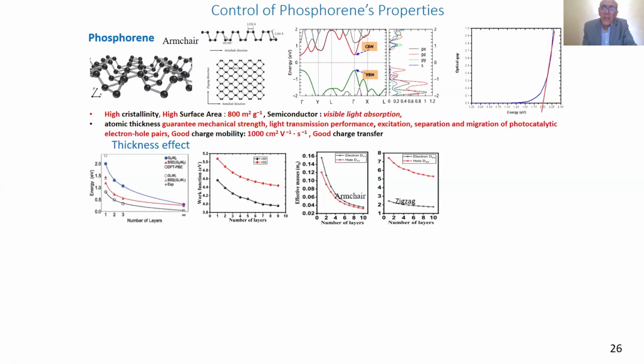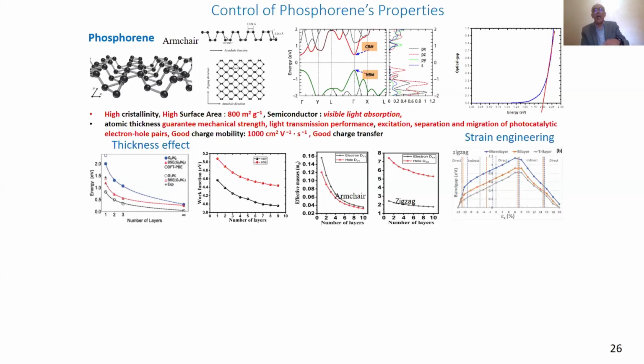We can also change the properties by strain engineering. All these results are obtained using density functional theory. As you see, without strain, we have a gap, but we can increase this gap by some tensile strain or decrease it by compressive strain. And at the same time, if we increase it more, we can change the behavior from a direct band gap to an indirect band gap. So we can tune the band gap by applying strain.